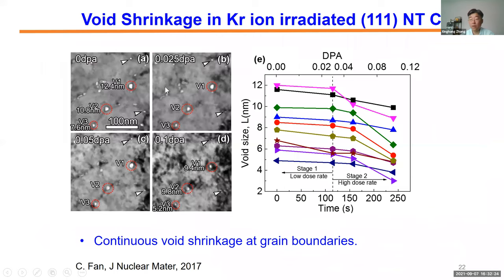So now if we look at what happened to these nano voids, that is a big question to us because we all anticipate voids should grow. But if you look at this, just krypton ion radiation alone, one MeV, if you trace this to about 0.1 dpa for several voids, one, two, three, you find out all these voids reduce their diameter. It's pretty much universal. Everybody shrinks, nobody grows in this case.